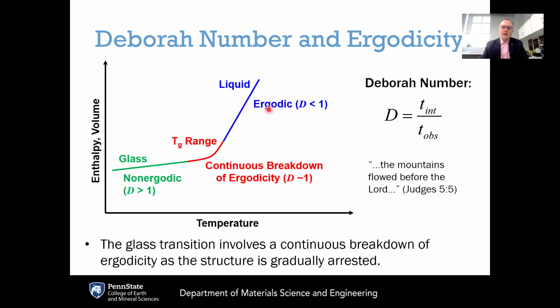So we have different regimes of the Deborah number based on this ratio of the internal to external timescale. If we have a liquid, it has a Deborah number less than 1 because everything that is happening in the liquid is happening on a very fast, very short timescale relative to our observation timescale, which means that the numerator here is less than the denominator, so the Deborah number is less than 1. This corresponds to an ergodic system because any relaxation process that needs to take place in that liquid is happening on a much faster time scale compared to our observation. And therefore, time averages of properties would be equal to ensemble averages of properties in the liquid because it's able to equilibrate on such a fast time scale. So ergodicity implies that the system has equilibrated on the time scale of our observation, and the liquid is in an ergodic state.